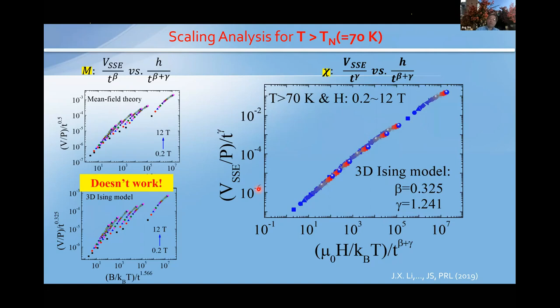So this tells us that magnetic susceptibility in this case worked very well if we treat the spin Seebeck voltage as something like magnetic susceptibility. From the fluctuation dissipation theorem, we know that we really probe the correlation of the spin fluctuations, right, the gamma. So from this exercise, we can conclude the spin Seebeck effect does not directly probe the order parameter, but rather the spin fluctuation correlation, in this case near the antiferromagnetic phase transition.